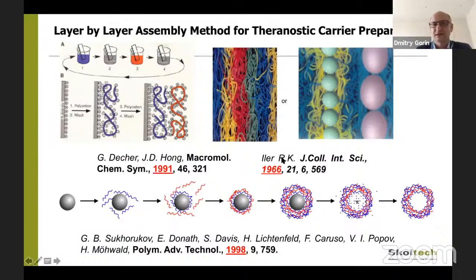And Iler used an optical method for detection to show that he realized layer-by-layer assembly, that layers adsorb layer by layer. A little bit later, two researchers that were working at this time in Germany, in Mainz, suggested using polymers instead of nanoparticles. It's cationic and anionic polymers. And of course, you can use not only polymers, but you can combine polymers, molecules, and inorganic nanoparticles like magnetite, zinc oxide, and others. And a little bit later, in the end of